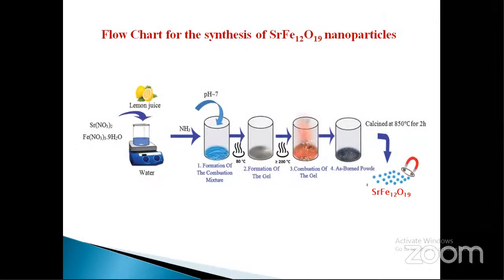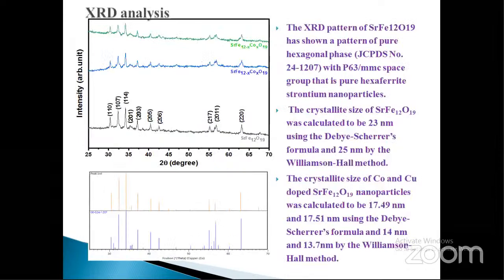This is the graphical abstract of the strontium hexaferrite nanoparticles. I have doped cobalt and copper. I have chosen cobalt and copper for doping in strontium hexaferrite nanoparticles, and this is the XRD pattern for the undoped material,